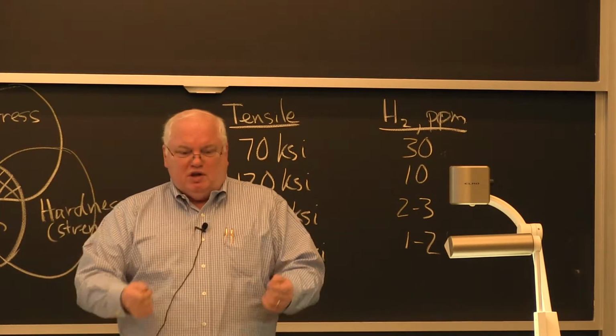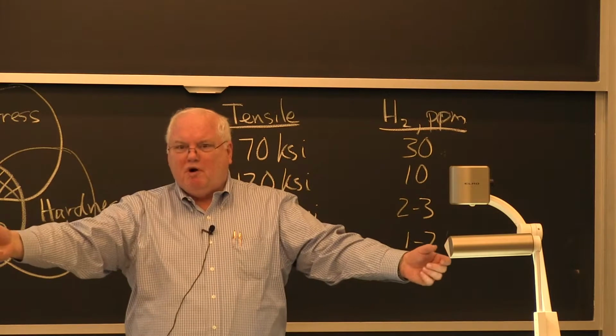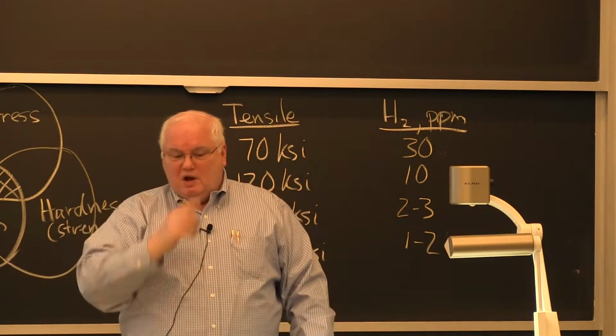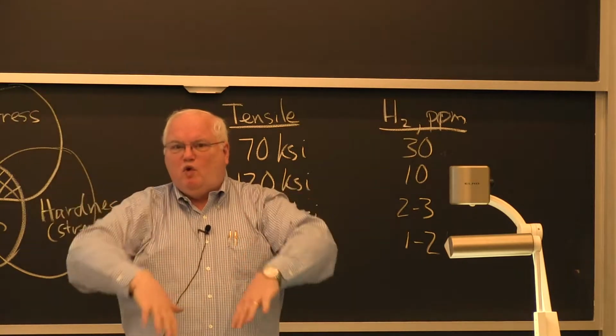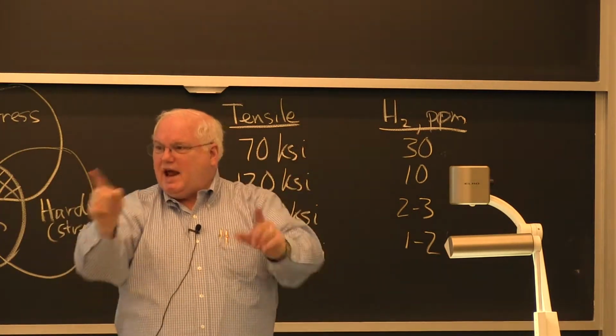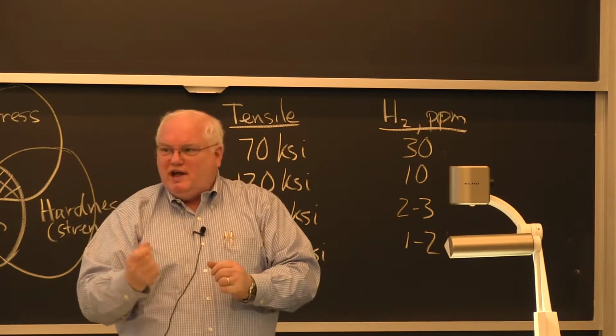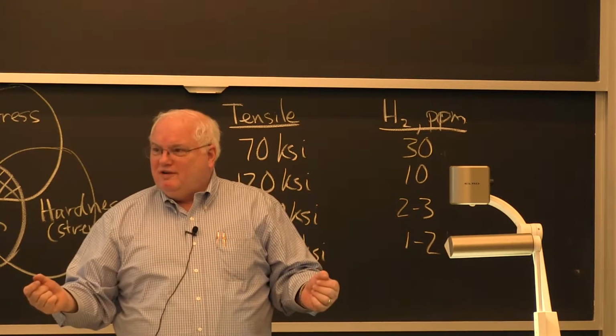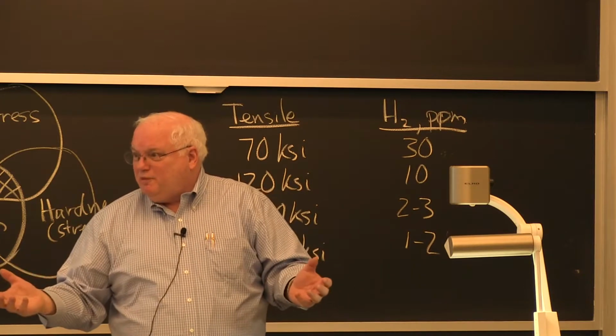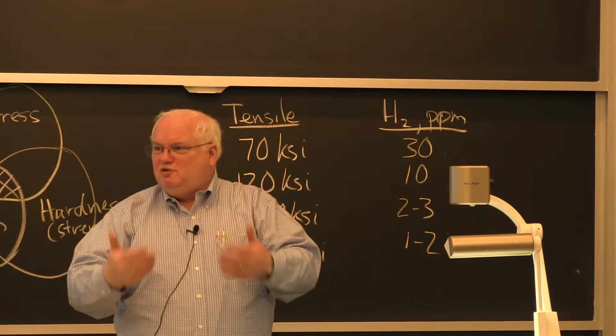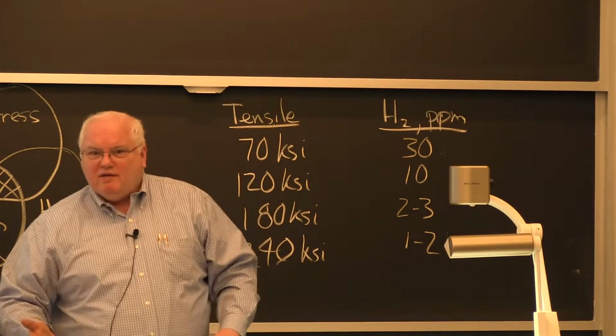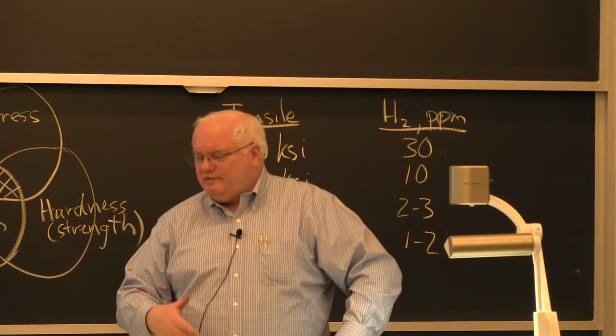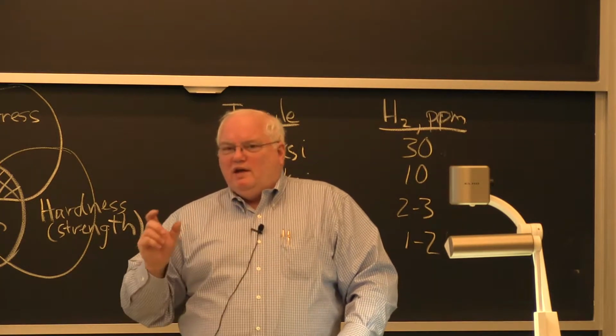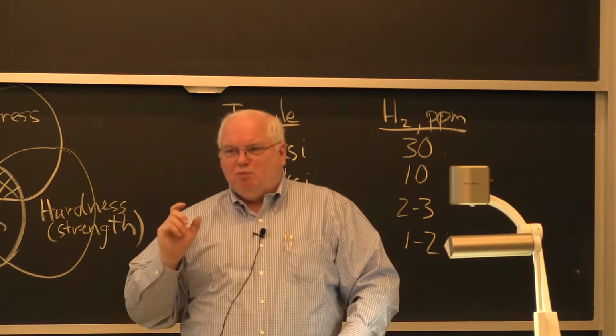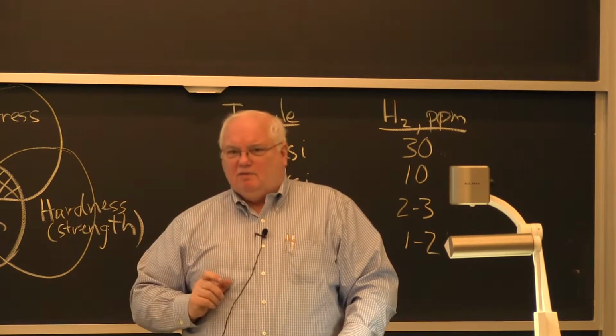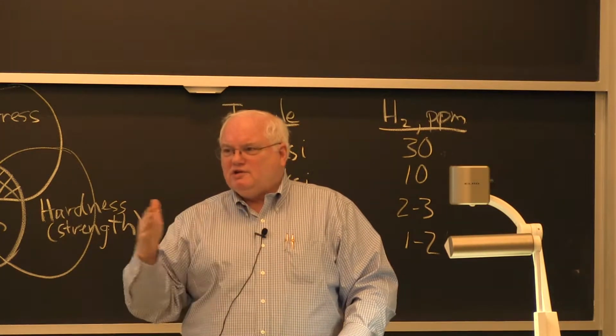So what do they do? They put the mic, which is just a big bar mic, to measure this 42 inches. They put it right on the bed that was filled with oil while they were machining, so it'd be at this exact same temperature. Because the measuring tool has to be at the same temperature as the part you're measuring, or you're going to get an inaccurate measurement, right? So they bathe the measuring tool in the same cooling bath and lubricating bath they did the other stuff. So again, I'm going to ask you, what is the world's most precise manufacturing in parts per thousand or parts per million of accuracy tolerance?